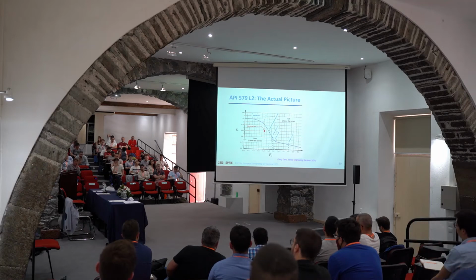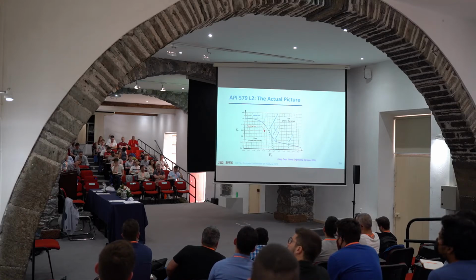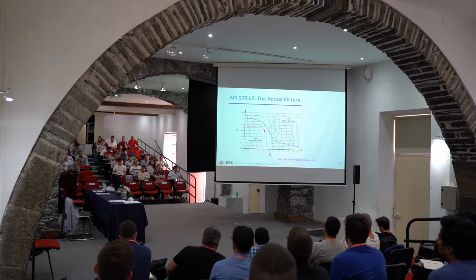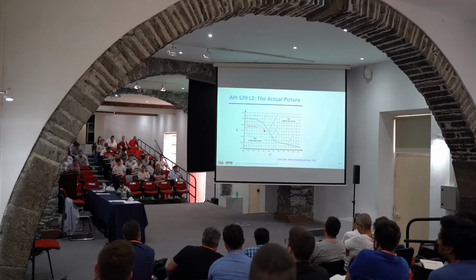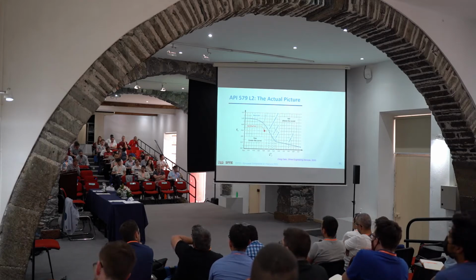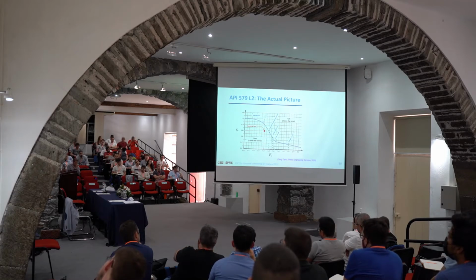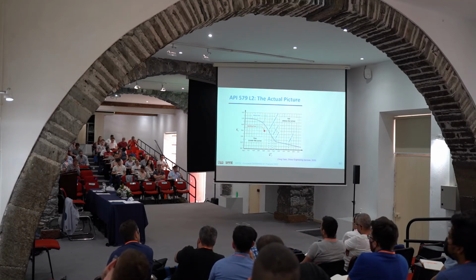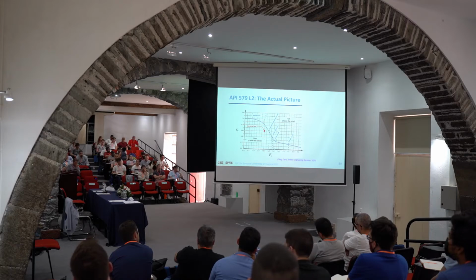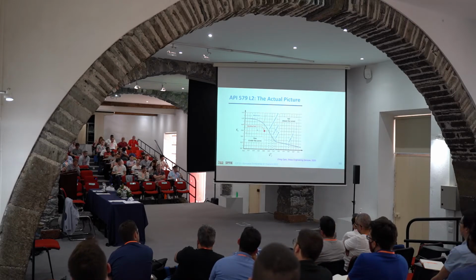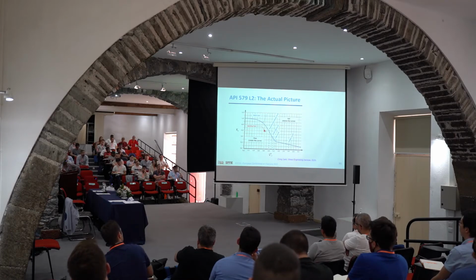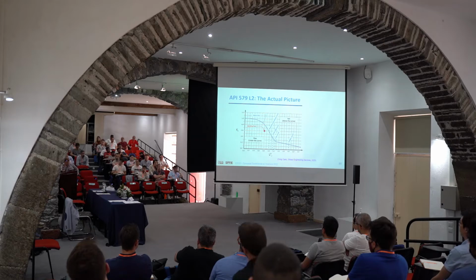So you divide the driving force by the toughness, and then you have the toughness ratio. Let's say it's 0.6. Then you go to the load ratio. Again, you have the internal pressure, the membrane stresses, circumferential stresses, PR over T for thin wall pipelines. Then you go to the code and get your reference solution, sigma ref. You know the yield stress of the material, and then you divide the reference stress by the yield stress. Then you have your other point here. So the intersection of these two points defines the operating point. It's as simple as that.